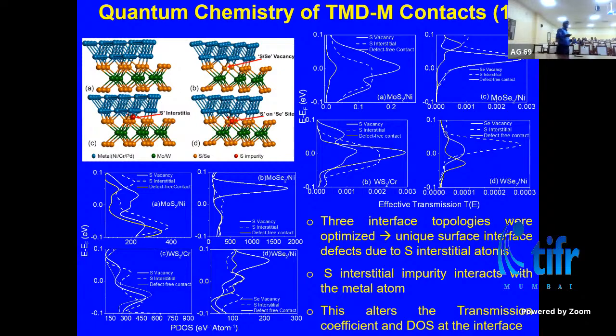So in TMD, these are different systems that we studied computationally first. We studied all different TMDs, sulfides and selenides of tungsten and moly, and we studied 3 different metals, which are nickel, chrome, and palladium, the most preferred or commonly shown metals in the literature, right? We studied this under 4 different scenarios. So 4 different TMDs, 3 different metals, 12 configurations, and then again these 4 different configurations. So we investigated around 48 different configurations computationally first, right?